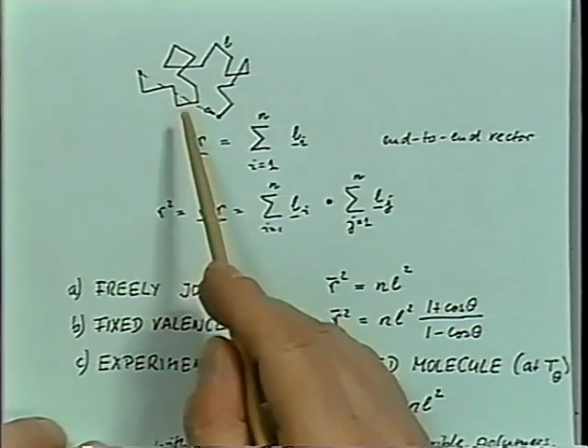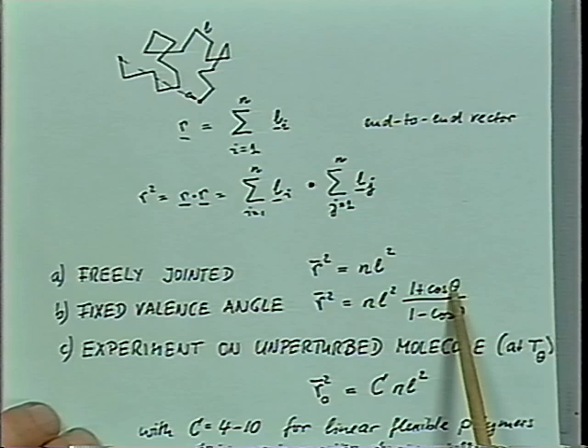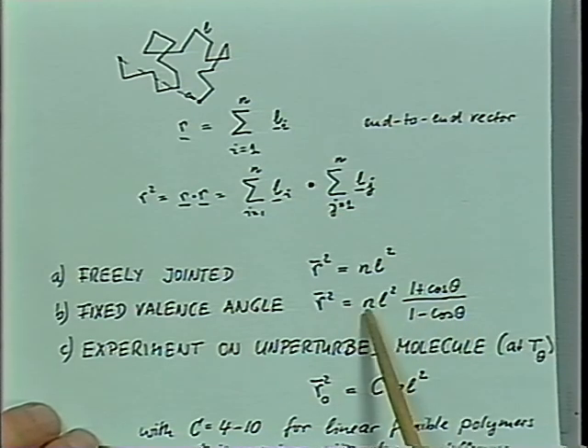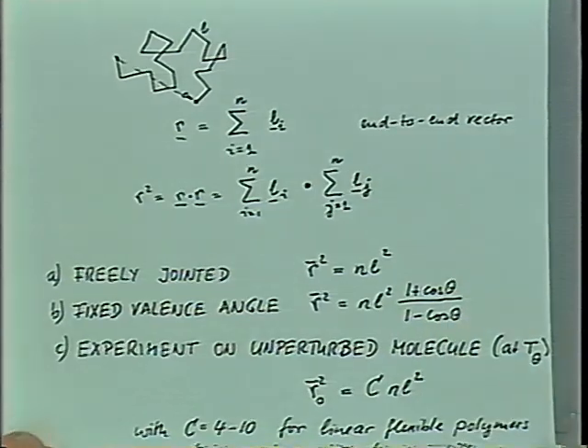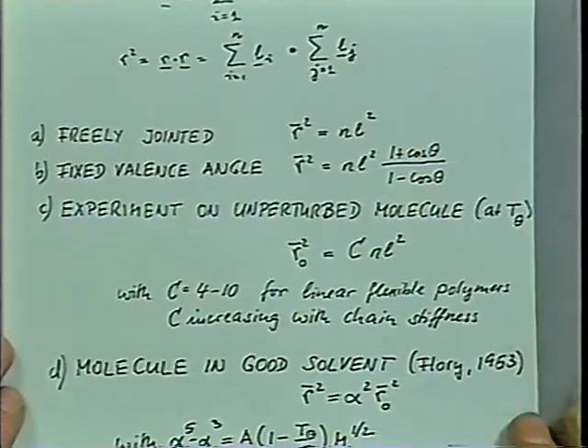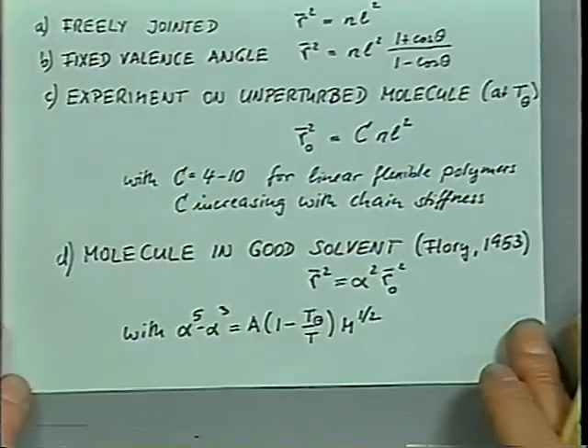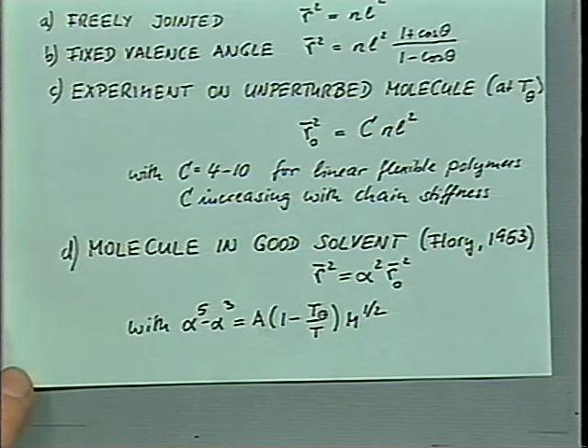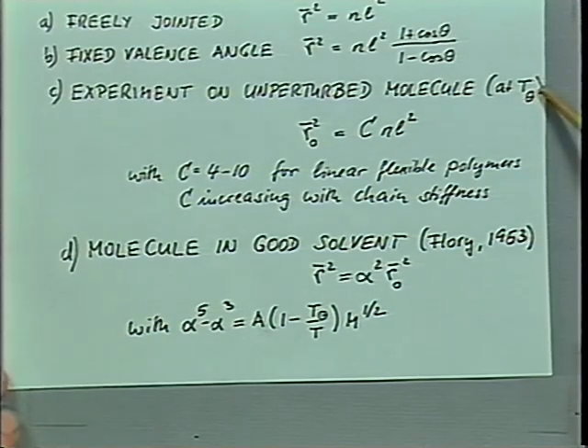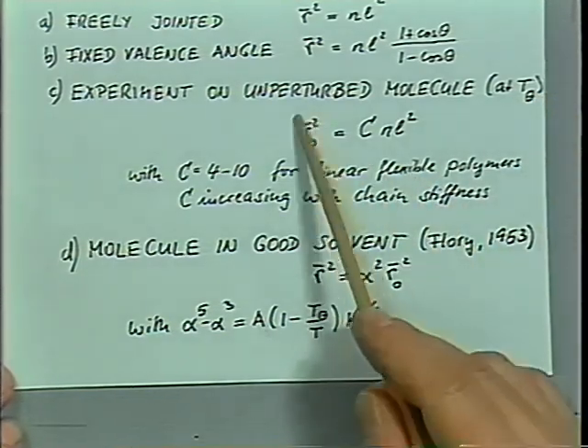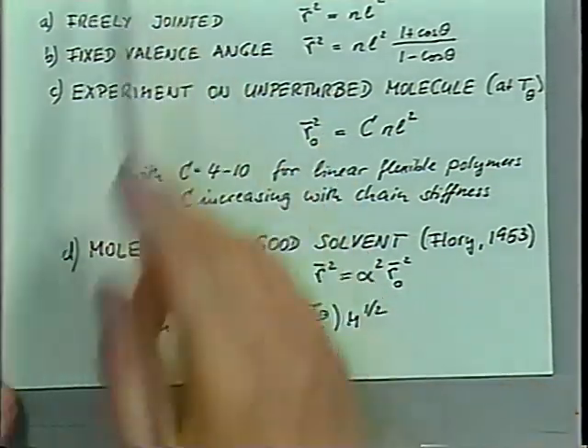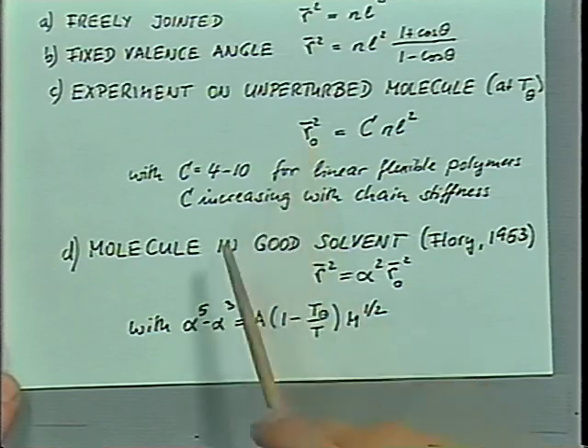Now, if the angles are somehow restricted with a valence angle of theta, then you can derive a similar equation. Again, it has n l squared and has this coefficient for the angle dependence. In a real experiment, you can measure the size of the coils by light scattering, for instance. In this case, you would pick a so-called theta solvent. That's a solvent which is neutrally interacting with the polymer chain. So it's a solvent at the theta temperature. And then you could measure the radius of gyration, which is related to the end-to-end distance.